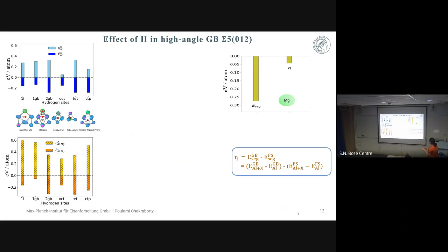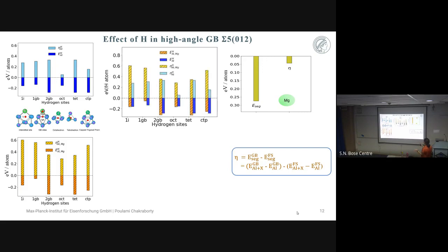And to top it all, this is the plot which shows the energetics of the segregation energy and the embrittlement energy of hydrogen in the presence of magnesium. As you can see, in the presence of magnesium, looking only at the lower curve, there is not much difference. The hydrogen segregates to the respective sites, maybe with a not very significant quantitative trend. But in the embrittlement tendency, the presence of magnesium enhances the embrittlement tendency when hydrogen goes and sits beside magnesium. This is further shown here in a comparison graph, where you can definitely see the differences.